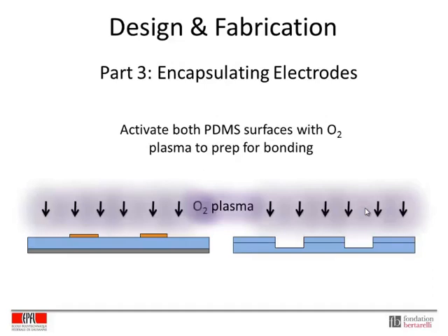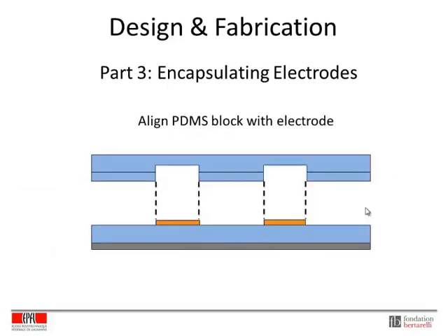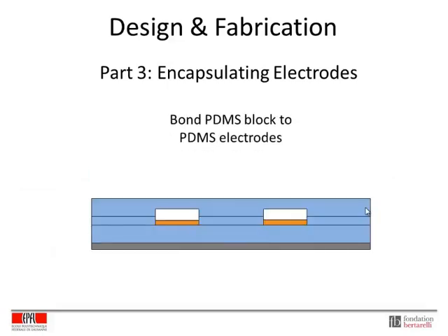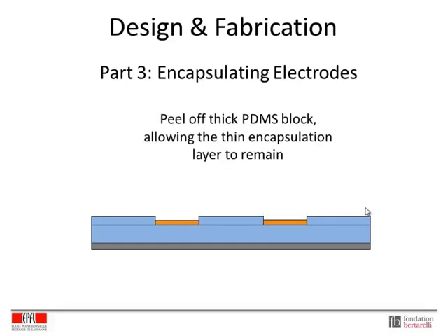Then we take the first two parts together, and before bonding, we activate the surface with O2 plasma. We align the PDMS block with the electrodes, and then we bond the two together. Finally, we peel off the thick PDMS block, which leaves behind just the encapsulation, which is just what we wanted. And then after we've wired up our electrodes with silver wire, we also end up peeling the entire PDMS features off of the silicon wafer.